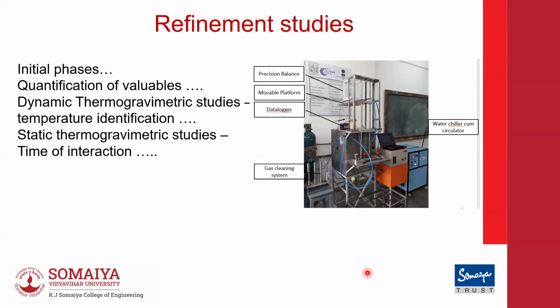Of late, what we have done is we have tried to separate and identify batteries of the same technologies, and then look at their XRDs before and after the processes, your initial phases. The variables were also measured: what temperature, what holding time. We did some thermogravimetric studies. Recently, we were actually able to extract cobalt metal as such. Although we are yet to determine the cobalt purity, the powder is pretty magnetic, which is a typical nature of cobalt. So we have achieved that level.